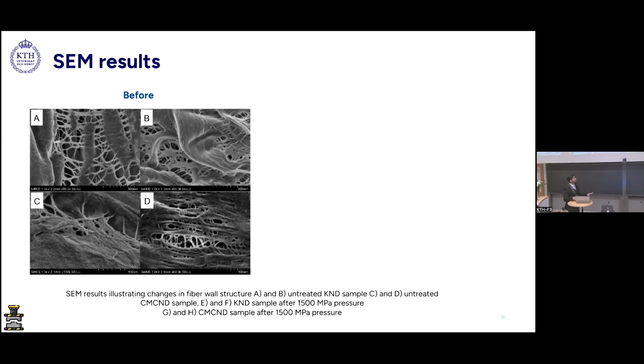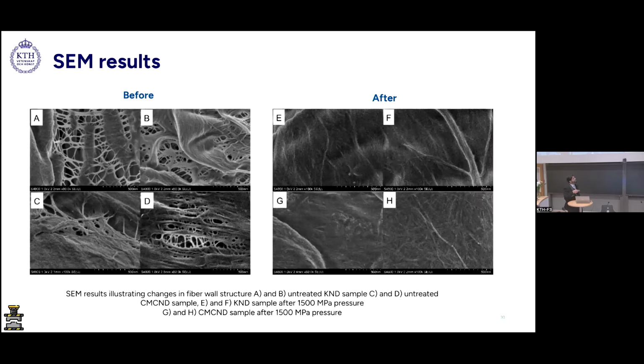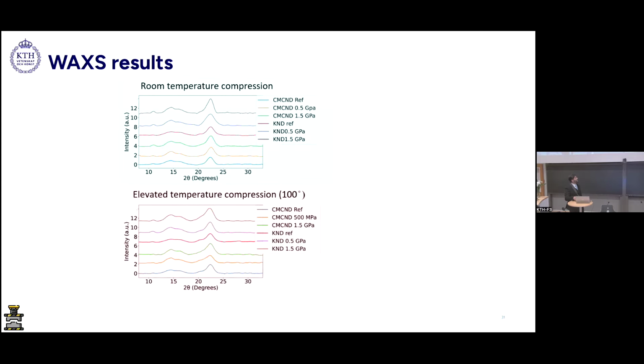At 1500 megapascals of pressure, we could see most of the pores were closed down, and the system looked completely different. So now we wanted to see the bulk measurement. As I said before, we did some wax measurement at room temperature as well as at elevated temperature. For Kraft pulp at both temperatures, we saw a little bit of increment in the intensity. Just from the visual perspective, there was a little more intensity of the 200 peak. That again indicated higher crystallinity of the sample.